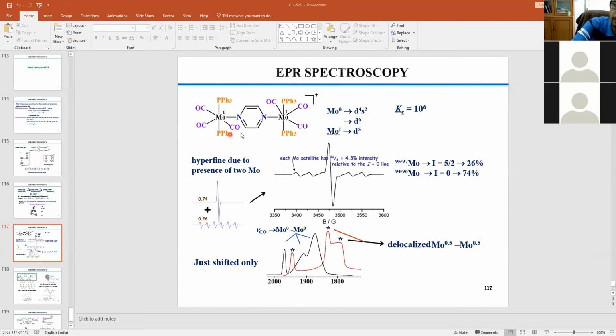If it is meridionally oriented, then you should expect the 3 carbonyl vibrations, which is known already from the IR point of view. Now, if you start with 0, 0, that the 2 moly are isovalent, absolutely isovalent, you take 0, 0, then what will happen? You cannot differentiate between these 2 molys, right? Because they are the same in all cases. Electronically they are also the same, 0, 0. And if you take 1, 1, the situation is the same. Electronically they are the same. So you should expect only 3 lines. For example, this is one, the black one. You see the 3 absorptions in the 0, 0, 3 absorptions in the IR.